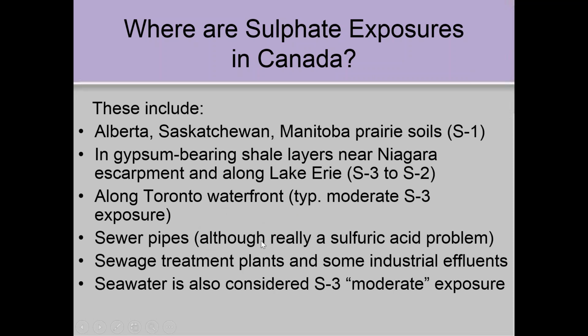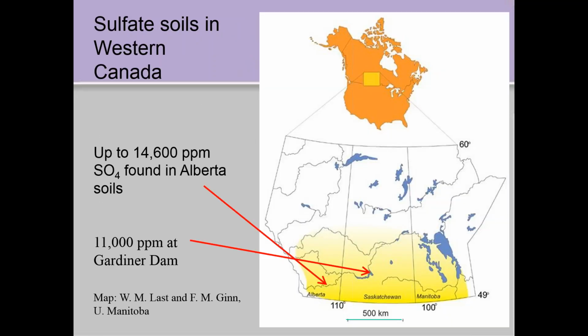And of course, there's problems in sewer pipes where we require sulfate-resistant concrete, although it's really an acid problem because of the bacterial acid formation. Sewage treatment plants, some industrial effluents, and seawater is considered a moderate exposure. In addition, of course, it's always chlorides because of the salt in seawater, but it's also a moderate sulfate exposure. So that's where the exposures are. And that just shows you where the exposures are in the prairie provinces. And of course, that extends down into the states, through the Dakotas, Colorado, and all that. They have some severe sulfate problems. And we're looking at high concentrations in some of these cases, which I've listed there. In Alberta, some of the soils, the Gardiner Dam in Saskatchewan, they had severe sulfates in the soils there.